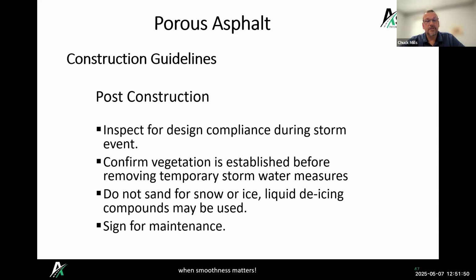Do not sand for snow or ice. We don't want to use regular road salt as well. Some liquid de-icing compounds may be used. What we found is with the porous pavement sections, typically we don't get a lot of ice or snow buildup. Obviously, when it snows really hard and really fast, snow can build up onto it.